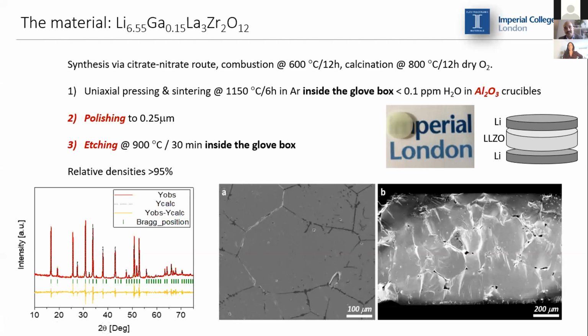After the sol-gel, the powder undergoes a series of thermal treatments, which are actually done in an alumina crucible. After that, we end up with round pellets of this kind of shape here, about 10 millimeters in diameter, which we polish down very finely, and we thermally etch them.